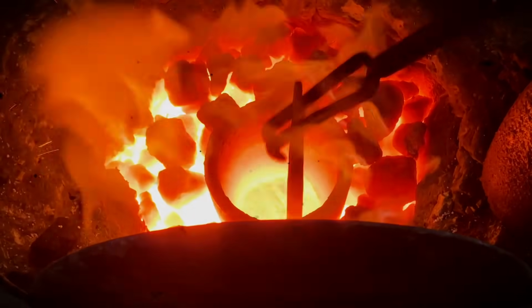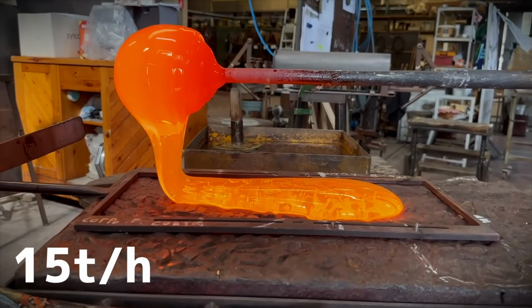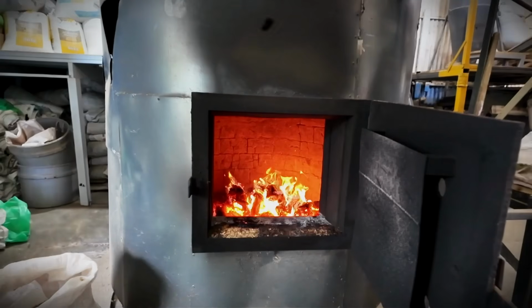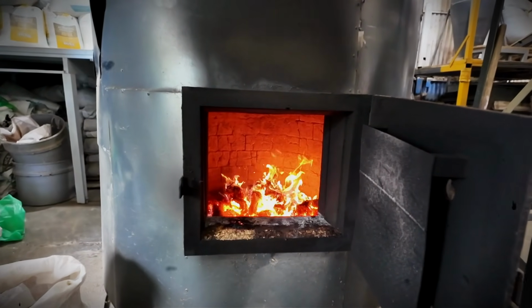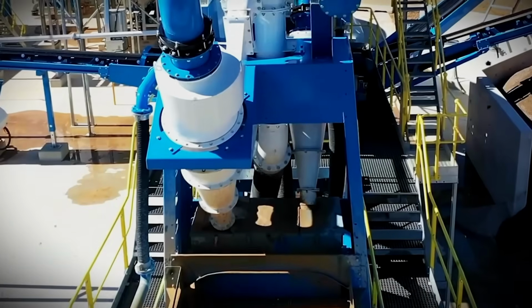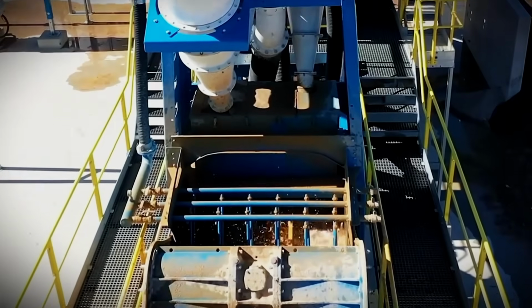Raw batch pours steadily in at 15 tons per hour. Over the next 16 to 24 hours, it slowly dissolves into molten glass. Workers monitor everything from a control room with over 50 thermocouples throughout the bath. Even a 10-degree deviation can ruin the entire batch.